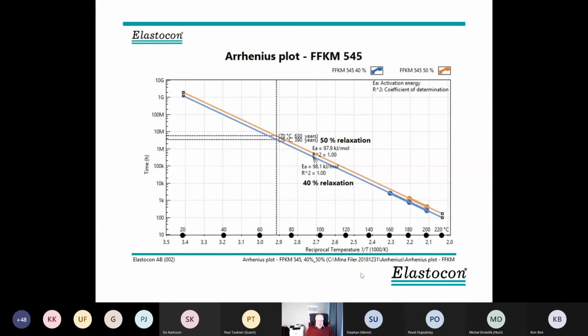So then we plotted Arrhenius plots for this. And we plotted both 40% relaxation and 50%. For 40%, we had 3 values. We got a nice straight line. For 50%, we had only 2. But if the 50% line follows the 40% line, I think we can still use the data for that.